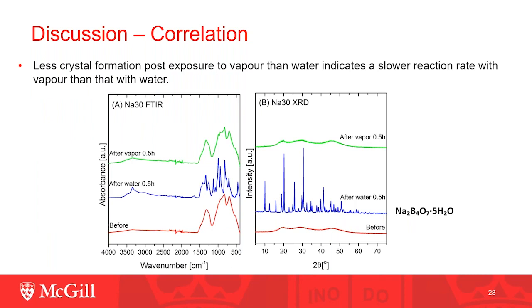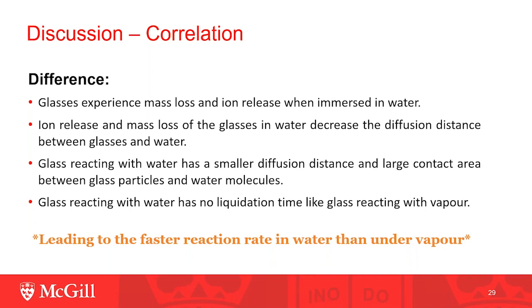However, there is a difference between dissolution and vapor absorption. For sodium-30 exposed to vapor for only 30 minutes, there is only small change in FTIR and XRD spectra, indicating sodium-30 is only beginning to form crystal. However, there is more new crystal formation when dissolving in water, indicating the glass has a more rapid reaction with water than with vapor. This is because there is weight loss and ion release when immersing in water, which decreases the diffusion distance between glass and water. Glass reaction in water has smaller diffusion distance, a larger contact area, and no condensation time like vapor-induced reaction, resulting in a faster dissolution rate than vapor absorption reaction rate.